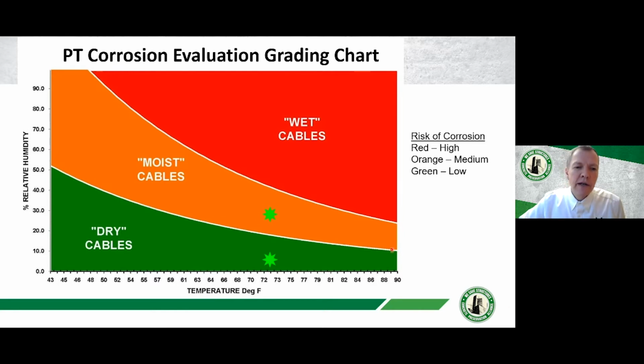If the moisture content is higher up here at the same temperature, then corrosion is definitely possible, but the corrosion rate will be limited by the moisture content that's there. And if you measure something up in the upper red zone here, then the corrosion rate is not limited by the moisture content. It may still be limited by other factors like availability of oxygen, but you have more than enough moisture there for corrosion to go at a significant rate.